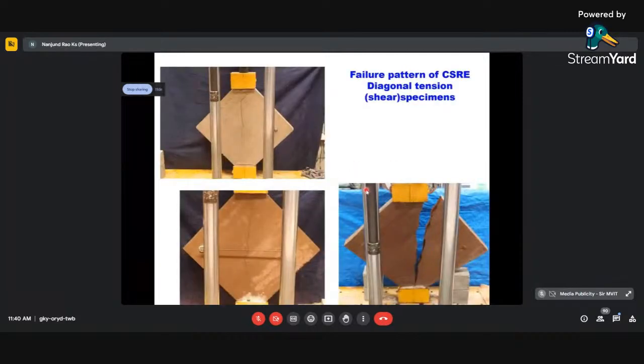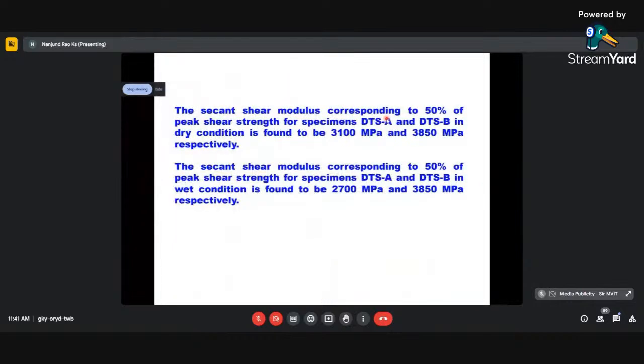These are, say, failure patterns of the test specimens. You can see in the wet condition, it has broken along the diagonal, the crack has come and broken. You can see the crack here, crack here. This is the failure pattern of CSRE diagonal tension specimens.